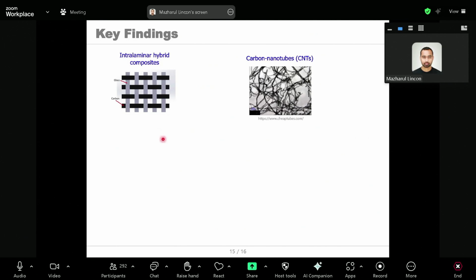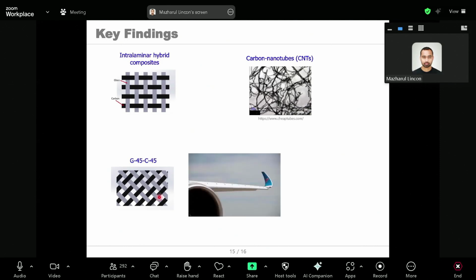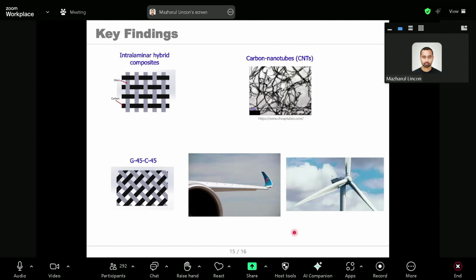This intralaminar hybrid composite, for G45, C45, 45 degree orientation ply, shows very good damage sensing capability as well as out-of-plane deformation. So this material can be a good candidate to make aeroplane wings or wind turbine blades, and it can also be used for continuous structural health monitoring of a structure to maintain its structural stability.